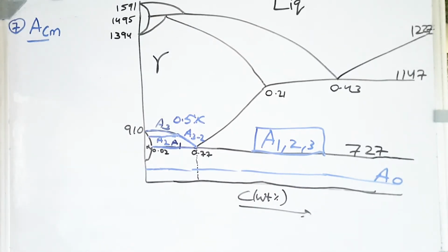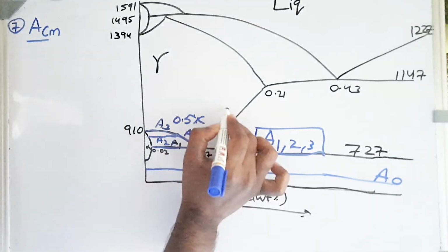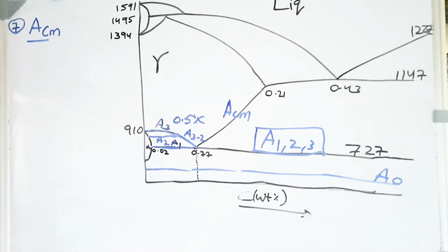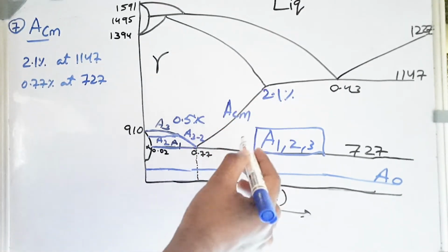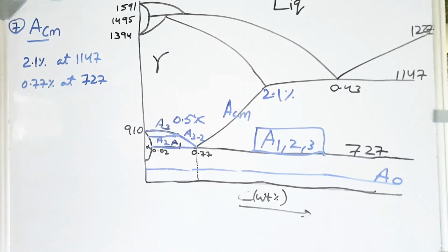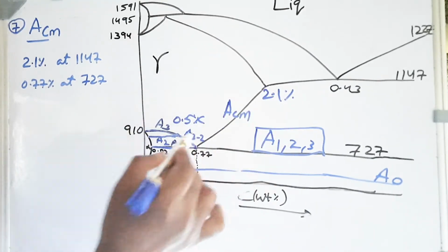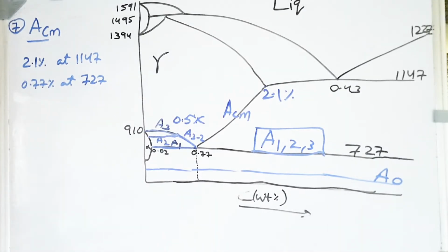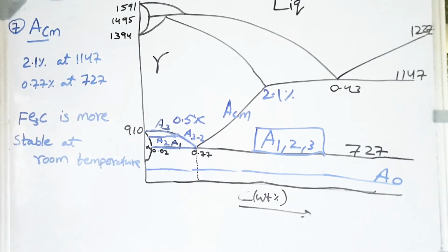Friends, now let's discuss ACM. In hypereutectoid steel, the composition of austenite, which is in equilibrium with cementite, is given by the ACM line. It is represented as this curve, friends. This is ACM. Friends, this ACM line illustrates that solid solubility decreases very rapidly, from 2.1 weight percentage carbon at 1147 degrees to just 0.77 weight percentage at 727 degrees centigrade, which is because of the greater stability of cementite at lower temperatures. The extra carbon precipitates as proeutectoid cementite. So friends, this sharp decrease in solubility limit is due to the greater stability of cementite at room temperature.